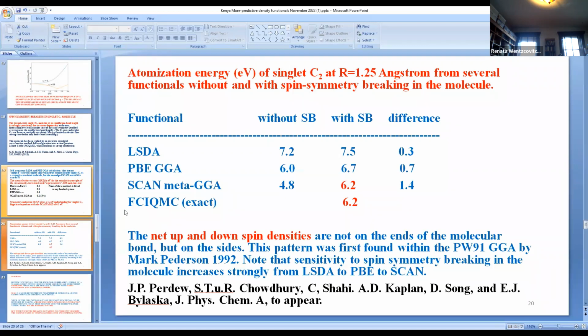If you look at what the symmetry breaking is, you see that in this molecule, which should be a spin singlet with zero spin density everywhere, the broken symmetry produces net up and down spin densities at different points in space. In C2, the net up and down spin densities are now not on the ends of the molecular bond, but on the sides of it. That's an unusual feature of C2.